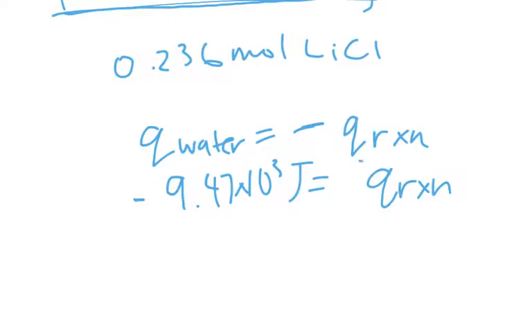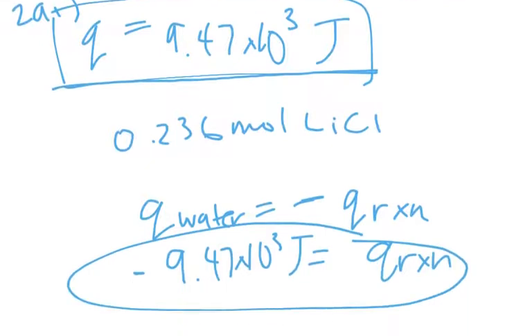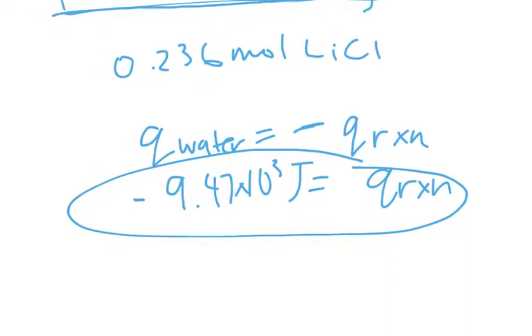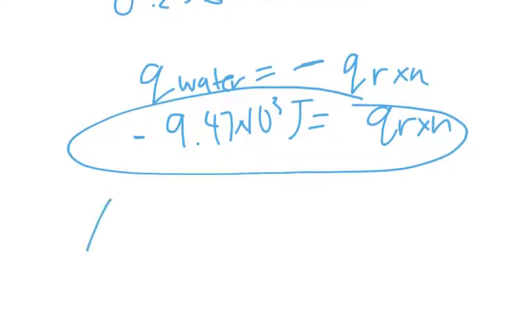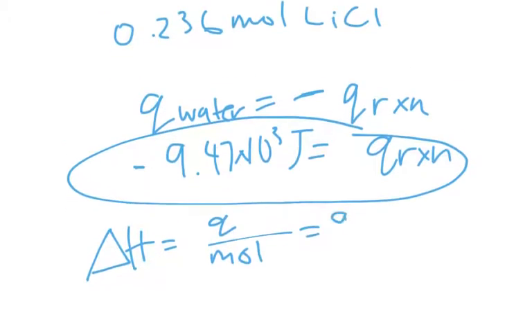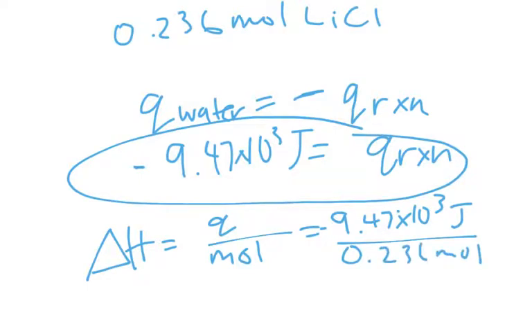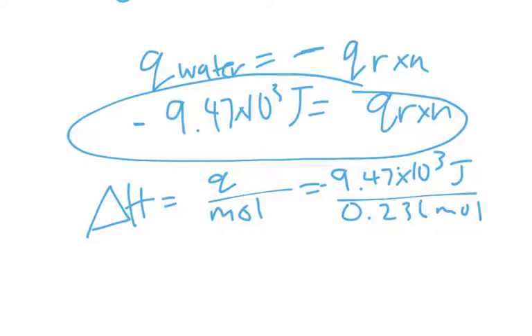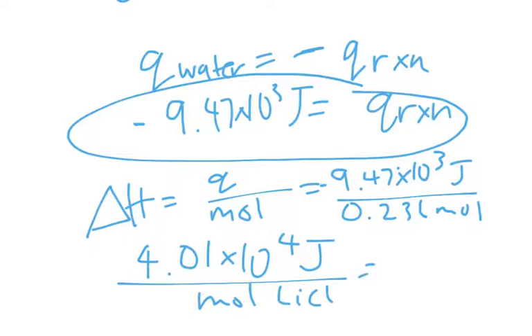And this makes sense since the reaction was exothermic because it heated up the water. So that means that the reaction must have a negative sign for the heat, or the delta H. And if we remember, delta H is equal to the amount of heat per mole. And we could simply plug and chug, so negative 9.47 times 10 to the third joules per 0.236 moles. And doing the math, we get, well, let's see, 9.47 times 10 to the third divided by 0.236. We get about 4.01 times 10 to the 4 joules per mole of lithium chloride as the delta H naught of solution.